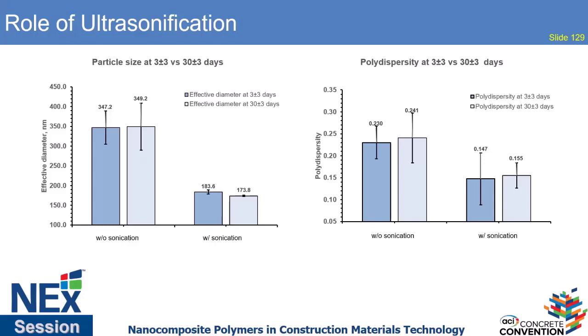sonication is very crucial, and it's a known method of dispersing nanoparticles. Our studies have also shown that just high shearing or using a rotor stator homogenizer for dispersing the nanotitania particles was not an effective method, and the size of the particle was reduced by half just by utilizing the sonication method as per the DOE in the previous slide. And this is also supported by the polydispersity, or the uniformity of the particle size sample.